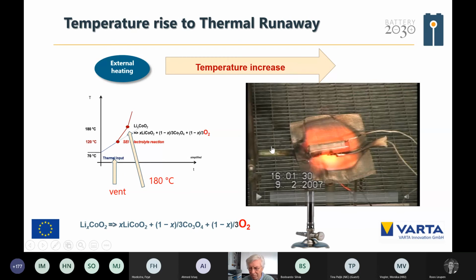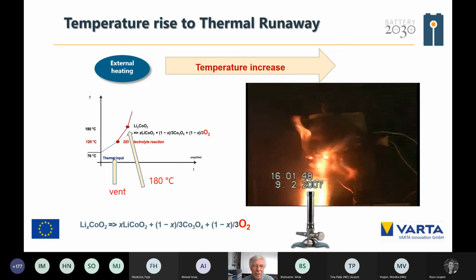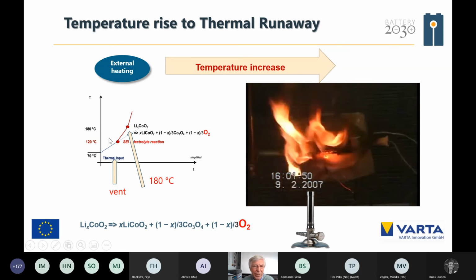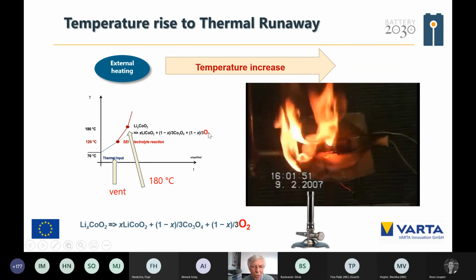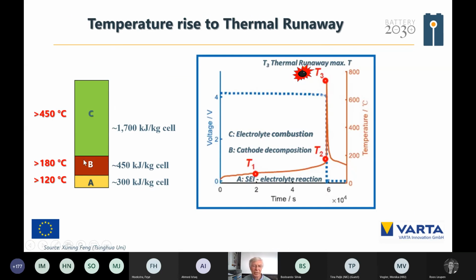We can repeat that or have the cell here. We have done that. Burning with the Bunsen burner. Here the vent is open, and now we are coming to the decomposition of the cathode material. At that point, the cathode material was decomposed, the oxygen was generated and reacts with the electrolyte and with the cathode. So, and you could see that again here. That is the SEI electrolyte reaction, cathode decomposition, and here the electrolyte combustion leading to a thermal runaway.